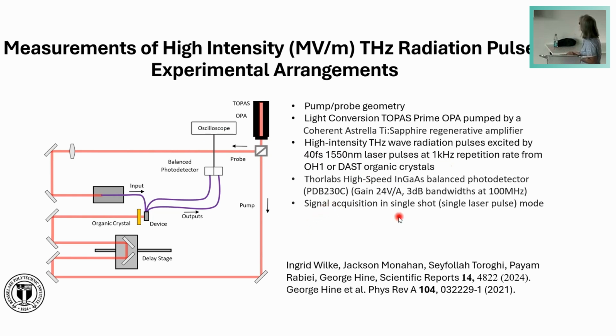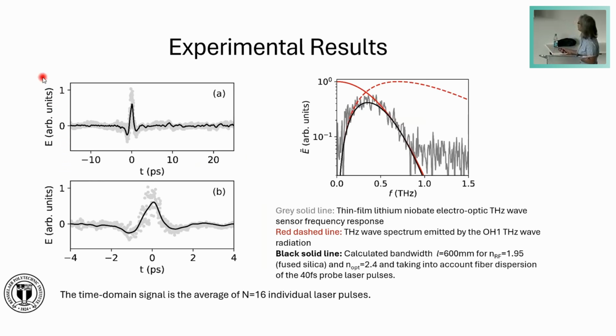This was a measurement where the signal acquisition was done in a single laser pulse mode. So the signal we got was really the signal from a single laser pulse. This is the result. We see an example of a time domain transient which we measured with the sensor using the system I just described. So we see the characteristic temporal shape of the pulse, like we would expect it if we use femtosecond laser pulses and organic crystals. And the black trace, this is a zoom of this area, represents the average of the signal of 16 individual laser pulses which were recorded. So we see here in gray the scattering of those 16 individual laser pulses.